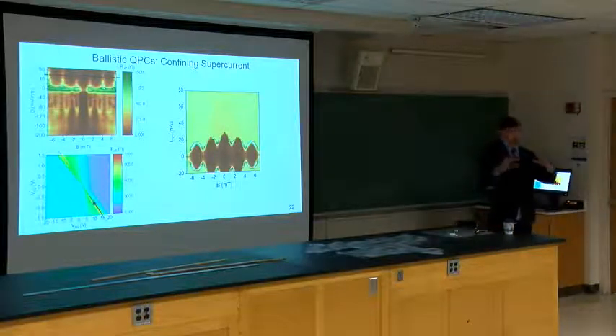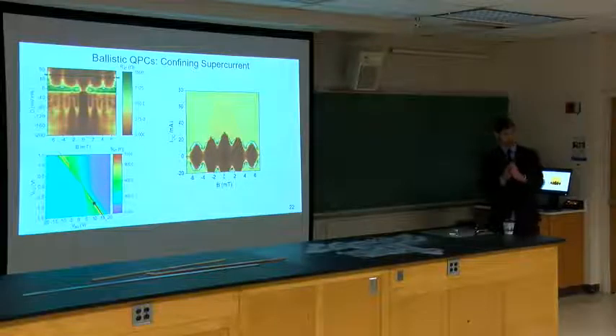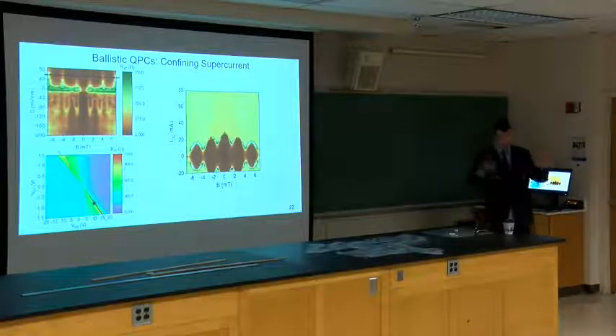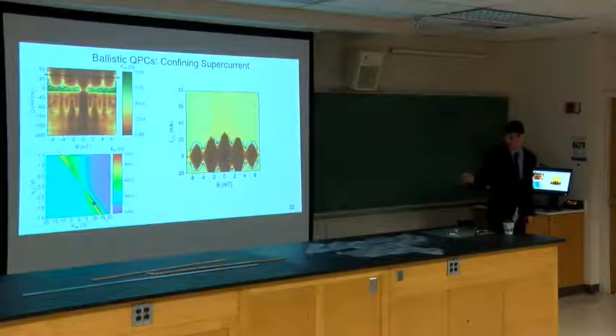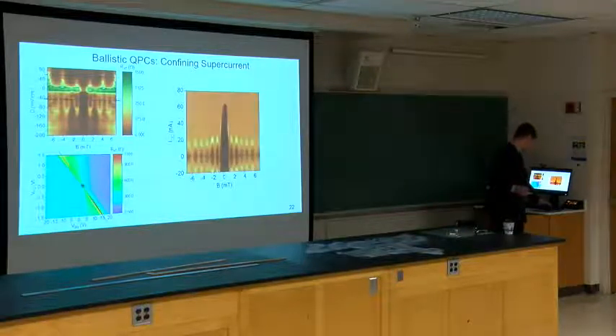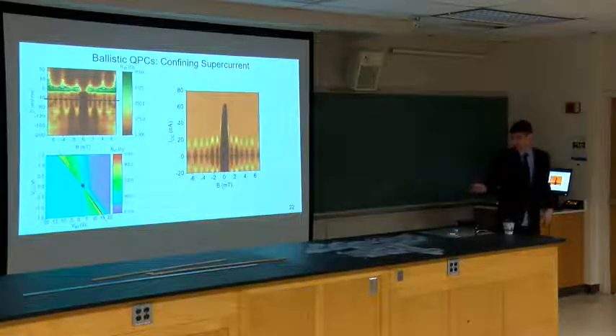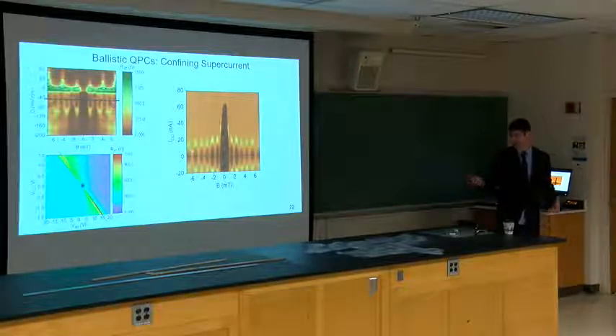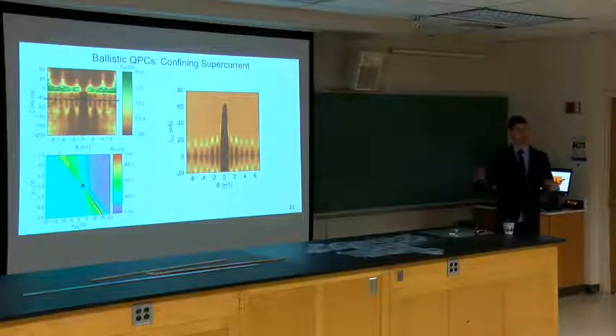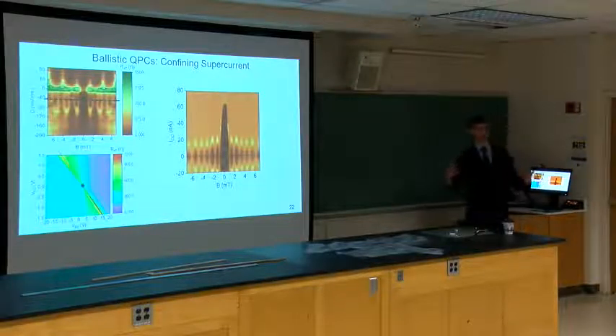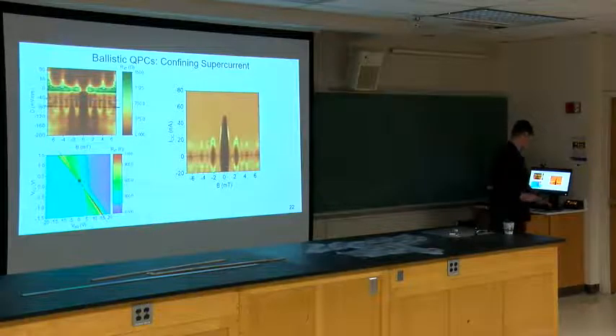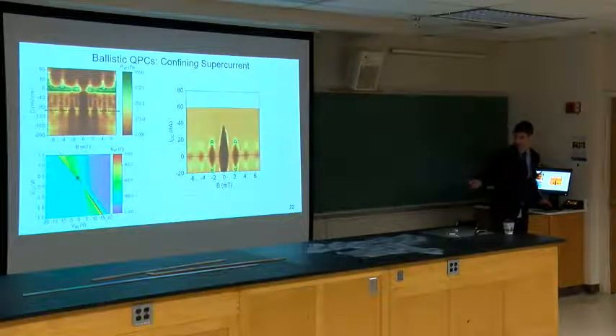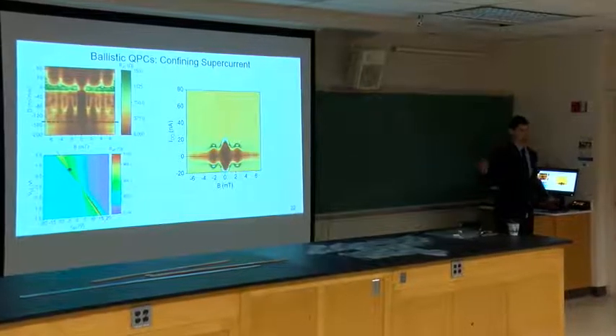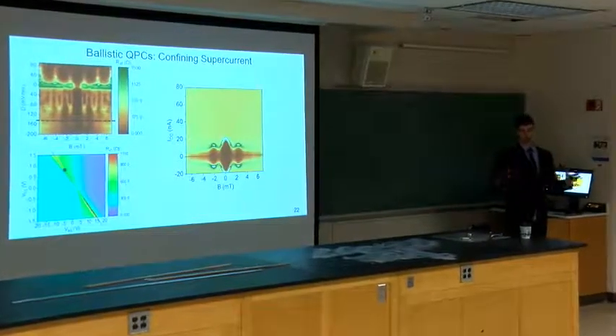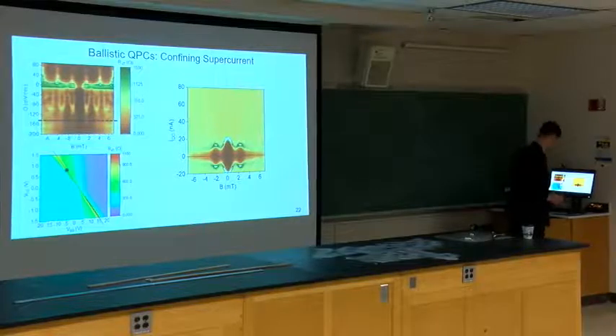At that point, the current is essentially confined to the central quantum point contact with a little bit of leakage on the outside, which is these resonances in the middle. But if we change the gate voltage so we have very little displacement field, we get a squid-like background pattern with a strong lobe in the middle. You don't have to take a lot of physics from this, but the idea is that it's telling us where the current is flowing. If we keep modulating the displacement field, it just keeps changing. We're changing in situ where the supercurrent can flow in the system.